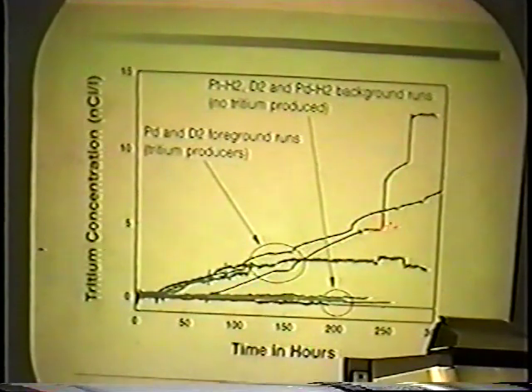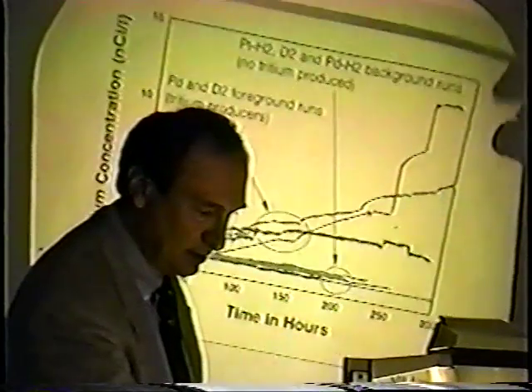Then we're pumping up the pressure in the system. And when you pump the pressure up, you actually get the quantitative amount of tritium because the cell is less efficient at lower pressures. So the ionization gauge doesn't really give you the right reading down here. All the slopes are pretty good. The other thing that you can see from this particular graph is that there are different slopes when we're running under different conditions. If we lower the current in the plasma, and if we raise that current, we do tend to get a little bit bigger slope. But again, if you go too far, you'll just start dehydrating the material, and what happens is that the effect goes away.